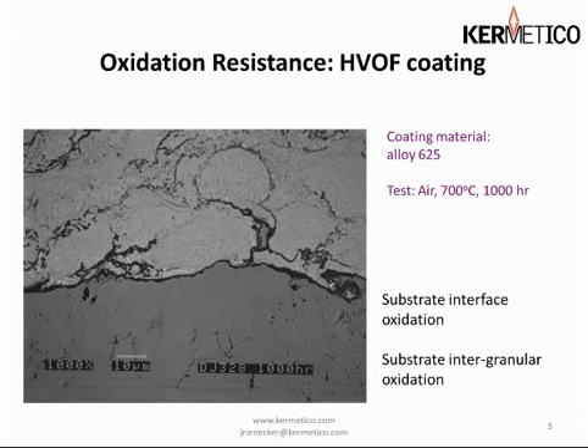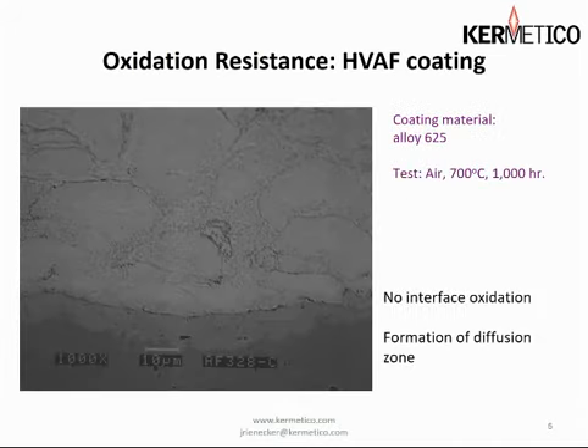What a mess - that didn't protect anything. Here we have our version of the coating, same thing, 700 degrees C, 1,000 hours. There's virtually no oxidation at the interface, very clean. No intergranular or interparticle oxidation in the structure of the coating. And most amazingly, you see a diffusion line. Now, if there was any serious oxidation at that interface, diffusion could not take place. So this is clearly a much better way to go for oxidation-resistant coatings.